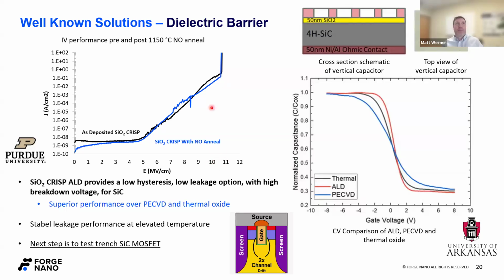So this tells us a couple of things. First of all, that our silica crisp film is very high quality. Second, it tells us that the nitric oxide anneal isn't really impacting these. So what does it impact? Well, we know that it does impact the hysteresis that we observe when we sweep in a CV. And so here on the right, as a transition, I should briefly mention, this is what the structures that we're measuring in both cases look like, roughly speaking.